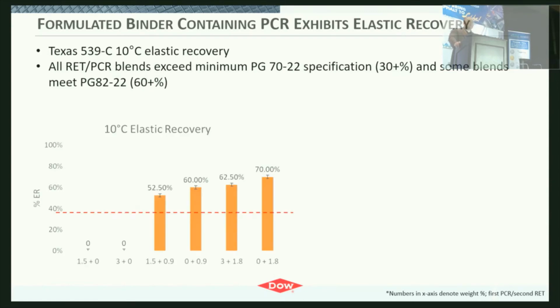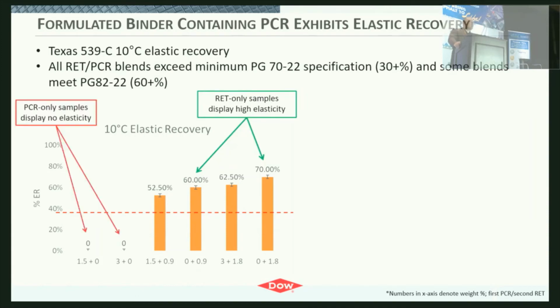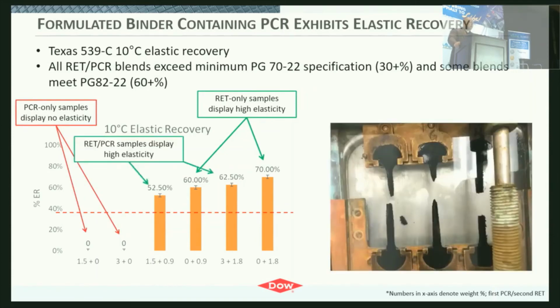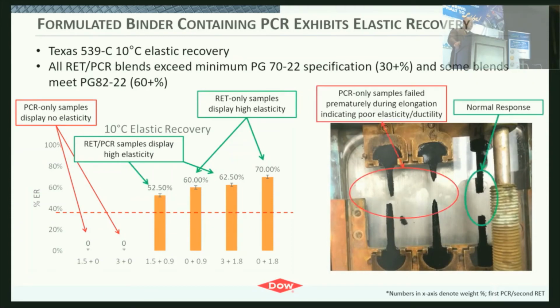So here we saw the similar trends as with separation, that the RET-only samples had high elasticity, 60 and 70% respectively for the 0.9 and 1.8% dosages. The PCR samples actually failed. They had no elasticity because they broke during elongation. And so here's just a side-by-side picture of the normal polymer modified in green and then the PCR only modified in red. Once you add the combination again, you do see an improvement that makes it more like the RET alone. And again, we're putting in 1.5% and 3% respectively of the recycled plastic.